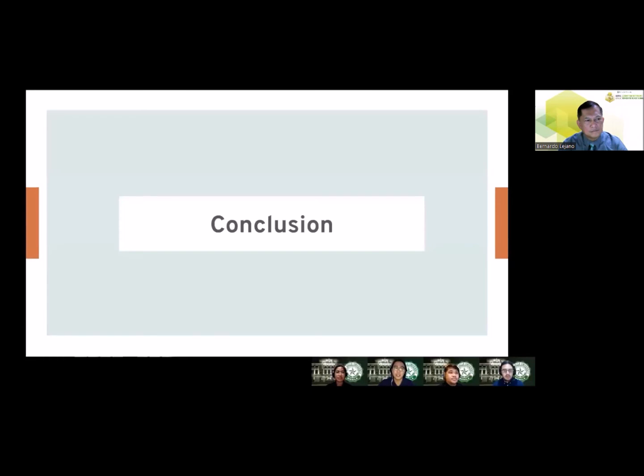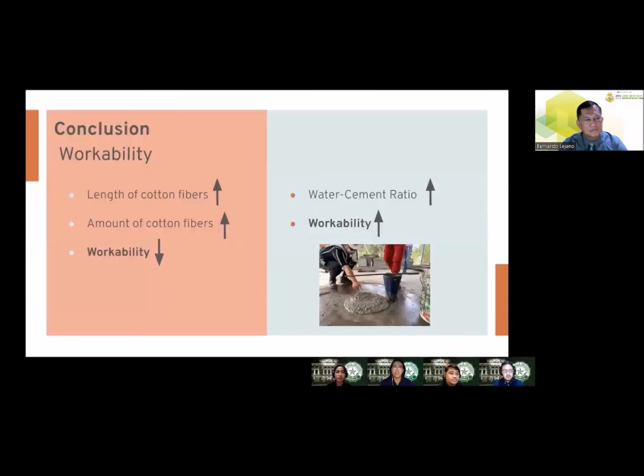Next, we have the conclusion. Based on the results of the slump test, the addition of longer cotton fibers and the increase of the amount of cotton fibers used resulted in a decrease in workability. Aside from this, the results showed that the workability values of the 0.6 water to cement ratio concrete mix were higher compared to the workability values of the 0.5 water to cement ratio.